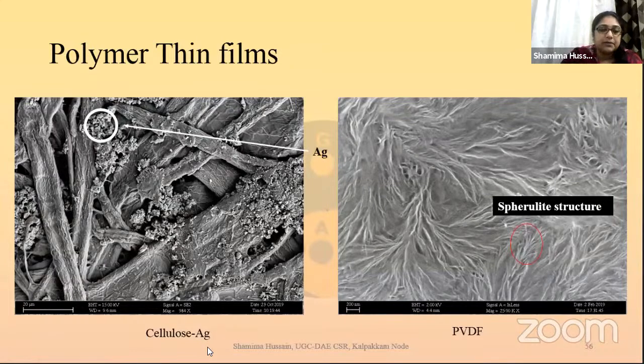Compared to this, you see here for the cellulose, we are using 15 kV. Working distance here is 4.4, that is between the pole piece and the sample. And this is what kind of lens I'm using. I can use the SE. For this one, I have used SE, secondary electron mode. Here I've used in-lens mode. Magnification is what I'm seeing here, 25kx. Here I've used 984x only. These are the information which you get in one particular image.